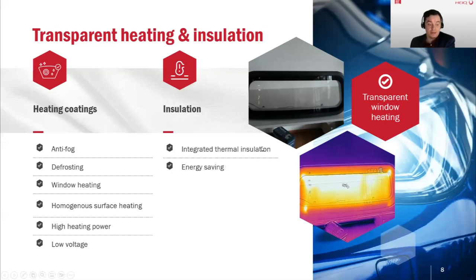For transparent heating, on the right-hand side here, you can see the back window of a car. It's a substrate that was coated together with a partner. We made this development with an industry partner, coated in an industrial process with HeiQ ECOS. Afterwards, bus bars were applied to have a contacting of the layers, and a top coat was applied to protect the silver wires and the layer against influences from outside, and to maintain a good mechanical stability and the stability against water, solvent, against abrasion resistance, and so on.